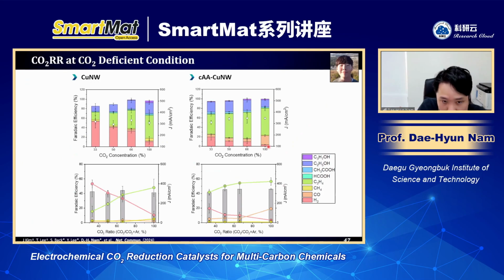And also to elucidate the role of this ascorbic acid, we also measured the CO2R in a CO2 deficient condition. It means that if ascorbic acid has an effect of capturing the CO2 and forming CO on the surface of the copper, this should also be effective in the CO2 deficient condition. When we compare the copper nanowire and the ascorbic acid one, we found a very interesting result. In the case of the bare copper, at low CO2 concentration, hydrogen was the major product because the CO2 concentration was very low. But in the case of the ascorbic acid based one, because ascorbic acid can promote the CO2 to CO conversion, although we lower the CO2 ratio, we could maintain the FE for ethylene over 40%. So this result also supports the role of ascorbic acid as a CO2 capturing agent.